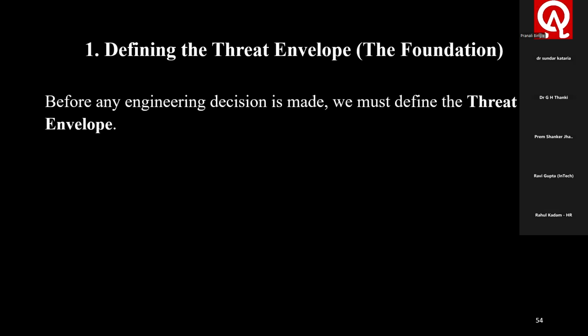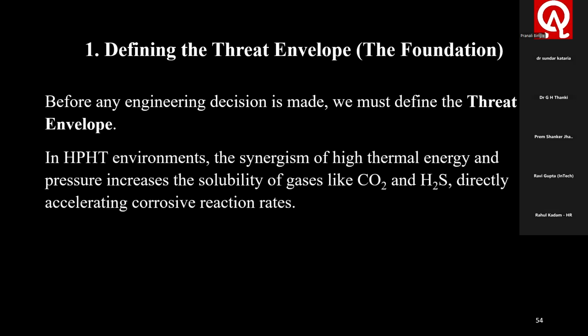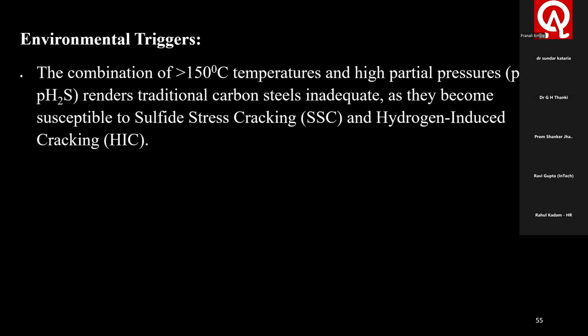Defining the threat envelope, the foundation. Before any engineering decision is made, we must define the threat envelope. What is that? In HPHT environments, the synergism of high thermal energy and pressure increases the solubility of gases like CO2 and H2S, directly accelerating corrosive reaction rates. The combination of more than 150 degrees centigrade temperatures and high partial pressures of CO2 and H2S renders traditional carbon steels inadequate, as they become susceptible to sulfide stress cracking and hydrogen-induced cracking.